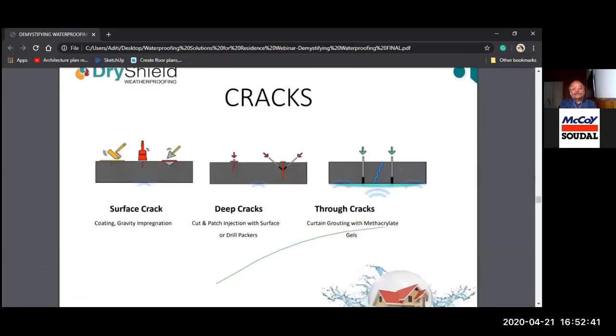So this is to show what type of cracks are there. Surface cracks can be done with coatings and some kind of gravity impregnation, maybe using some silane, siloxanes, or epoxies. And there are deep cracks which have to be repaired by cutting and patching, injection, and with surface or drill packers. There are through and through cracks which can be done only with gels.